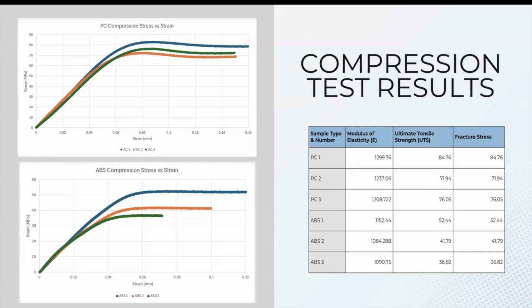Among the three, PC1 had the highest ultimate tensile strength at about 84.76 MPa, while PC2 had the lowest at about 71.94. Their modulus of elasticity ranged from about 1,208 to 1,299 MPa, showing fairly consistent stiffness across samples.